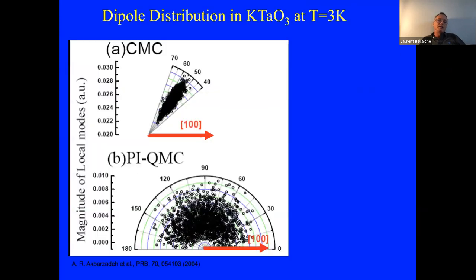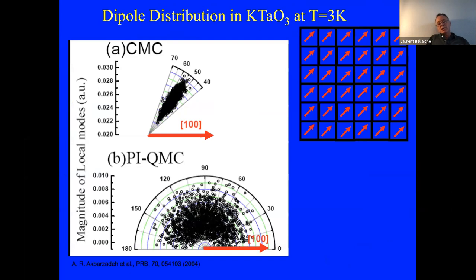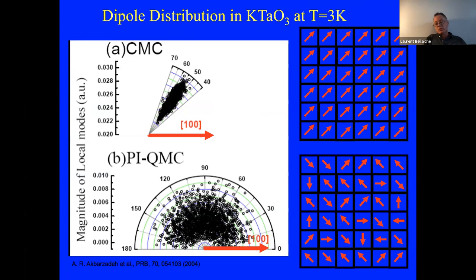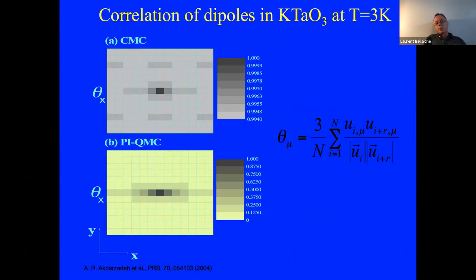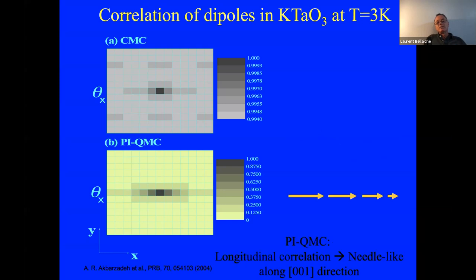We were able also to look at the distribution of electric dipoles. If it's classical Monte Carlo, this picture is showing you that basically they are all along 111 directions at low temperature. If quantum effects are being incorporated, you have a more disordered picture of electric dipoles. But it's not completely disorder. You can compute, this is what Alireza did, the correlation of dipoles. And what the first one is telling you is for classical, basically all the dipoles are 111. But for path integral quantum Monte Carlo, it's telling you that you have some kind of short range order between dipoles. If you have a dipole along X direction, if you go to its nearest neighbors along X, it also wants to be along X direction. Same thing for the second nearest neighbors along X, but the correlation is diminishing.